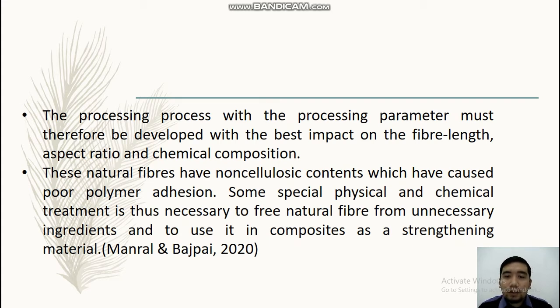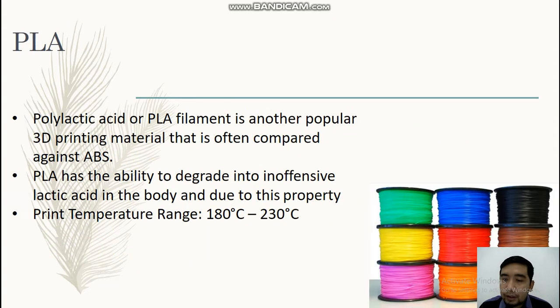The processing parameters must therefore be developed with the best impact on the fiber length, aspect ratio, and chemical composition. This natural fiber has non-cellulose content which causes poor polymer adhesion. Special physical and chemical treatment is thus necessary to free natural fiber from unnecessary ingredients and to use the composite as a strengthening material, by Manral and Bajpai 2020.